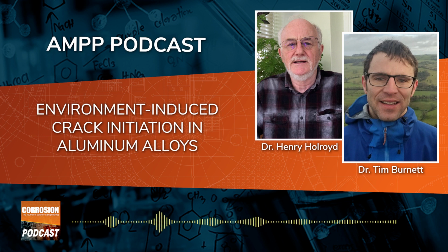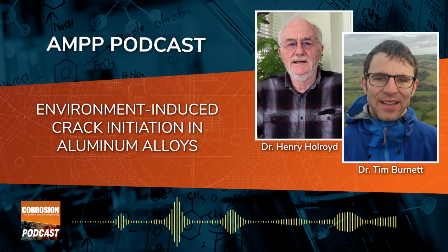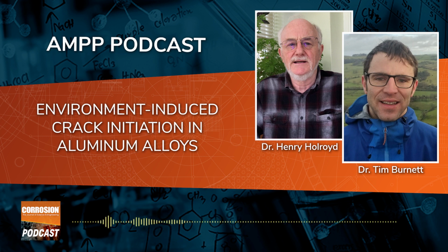So there's a lot of potential advances we can make in understanding initiation. One can argue that if a crack doesn't start, there's not a problem, because as we push materials, the industry is always wanting stronger, lighter materials, and we can get the toughness right. We can get the strength right, but more and more you find these cracking problems and secondary properties become challenged when you push materials. So we're now having to look at how we can get everything. We want our cake and eat it. So we need to study the very early stages, because we need to suppress that, because in some situations the growth rates are relatively high, which means you can't use that material.